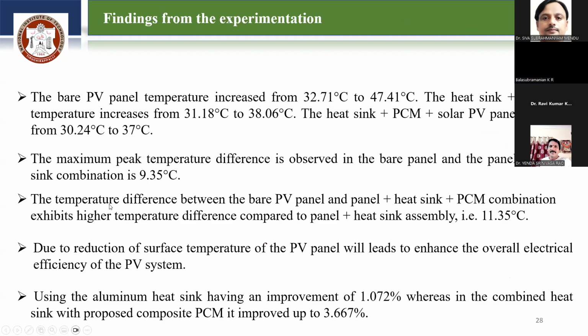The temperature difference between the bare PV panel and the panel plus heat sink plus PCM combination exhibits a higher temperature difference, around 11.35 degrees centigrade. Due to the reduction of surface temperature of the PV panel, the overall electrical efficiency is enhanced. Here we used the aluminum heat sink. This has an improvement of 1.072%, whereas in the combined heat sink with the proposed composite PCM, it further improved up to 3.667%.